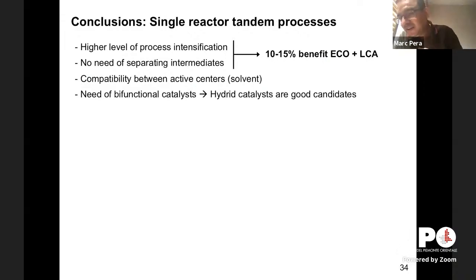Just to finish very briefly, key messages that we learned along this project and along this development of these single reactor processes. So these processes are interesting to have process intensification. That is something extremely important if we want to move to this new economy, to this greener economy. And of course, try to avoid separation of intermediates. And here the support of Solvay was very important because we could quantify all these benefits with very good eco-evaluation and LCA analysis. At ISO yield, comparing two-step processes with single reactor processes, our benefit could be between 10 and 15%. More or less, that could be general for different reactions.